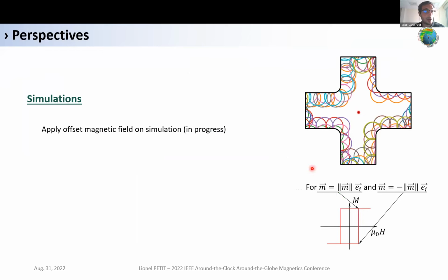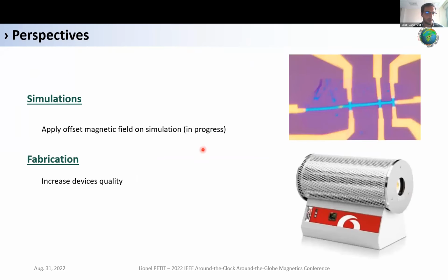To conclude, I will continue to make more simulations, especially with offset in magnetic field to simulate out-of-plane cycles, because I expect that some areas will not be sensitive. I will try to increase the quality of my devices, for example, by annealing them to remove this kind of blisters that you can see here.